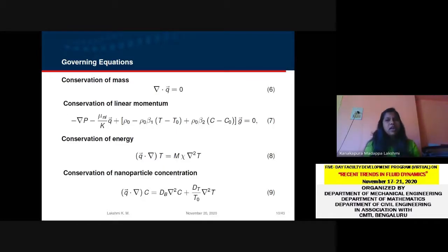In the Buongiorno two-phase model, we include two slip mechanisms which are important in the heat transport study, Brownian diffusion and thermophoresis, with coefficients given in equation number 9. Here dB represents the Brownian diffusion coefficient and dT represents the thermophoresis diffusion coefficient. On neglecting these two effects in the present study, we can obtain the results of the KVL model at a later stage. So for that reason, we have used the modified Buongiorno model for the nanoliquid and the Darcy model for the porous medium.